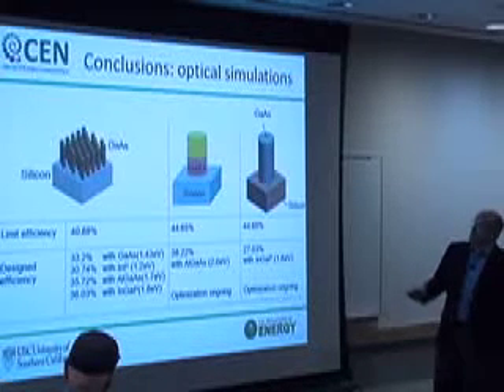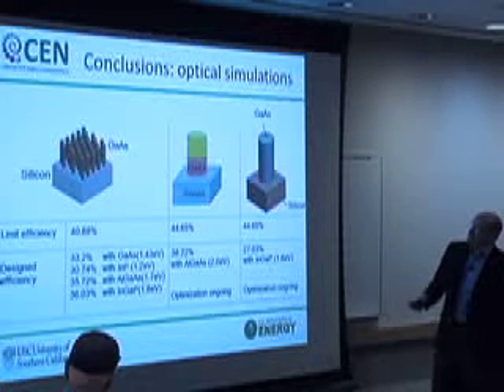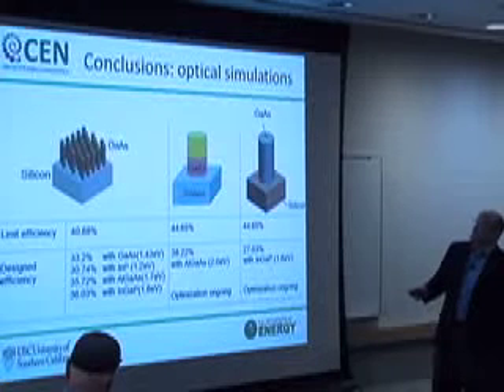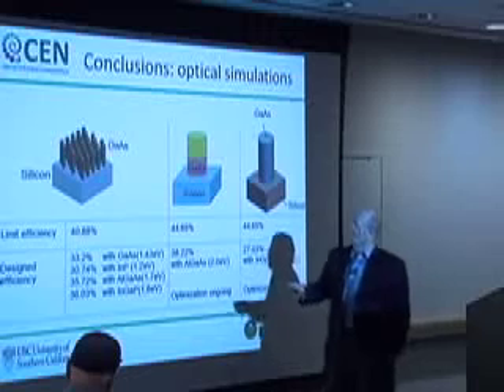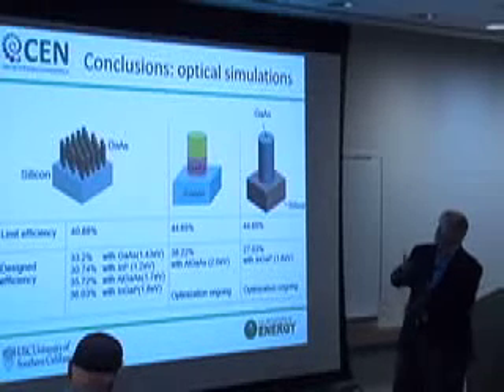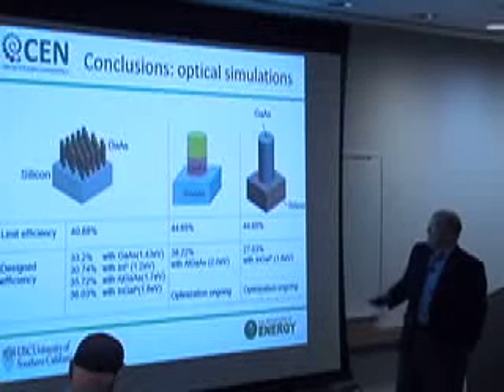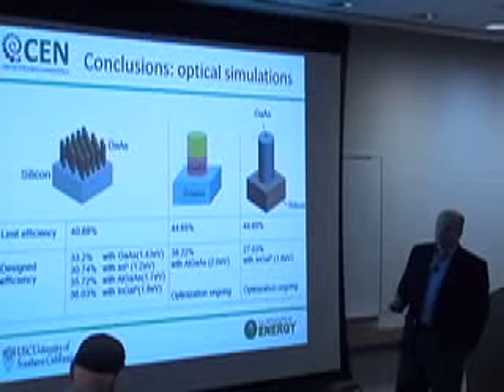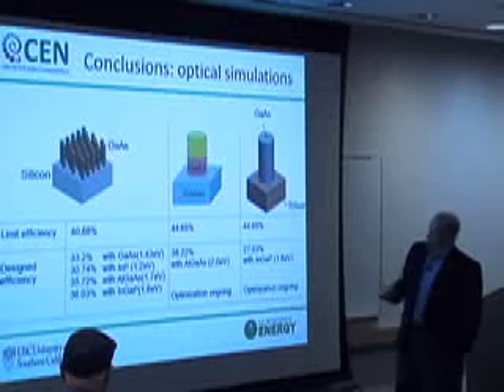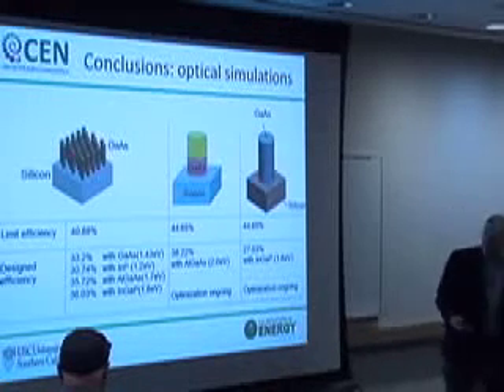Okay, so I'm just going to flash up a few results that she, or her group, has modeled. Gallium arsenide directly on silicon. It turns out that we can achieve nearly the limit efficiency with gallium arsenide on silicon, even though they're not exactly current matched. And we do that by limiting the height of the nanowire so that some of the light gets absorbed in gallium arsenide and some of it that's above the band gap leaks through and gets absorbed in silicon so that we can current match the structure. She's looked at gallium arsenide along with AlGaAs and indium gallium phosphide, and the numbers that she's calculating are very respectable efficiencies on the order of 30 to 40%. In all of these cases, we're looking at the nanowire solar cell as a way of enhancing the efficiency of the silicon cell in the short term. In the longer term, we'll be more aggressive.